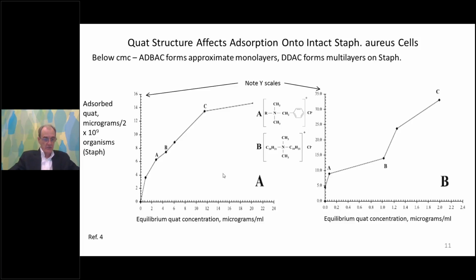So adsorption isotherms, a major concept in surfactant science, can be measured. So here we have on the y-axis the amount of quat adsorbed onto 2 times 10 to the 9th intact Staph aureus organisms as a function of the equilibrium quat concentration. And we have 2 different quats. We have our ADBAC on the left and our DDAC type on the right. Very different scale, notice on the Y scale. The DDAC adsorbs significantly more onto the Staph aureus organisms, and it seems to have a quite different shaped adsorption isotherm.